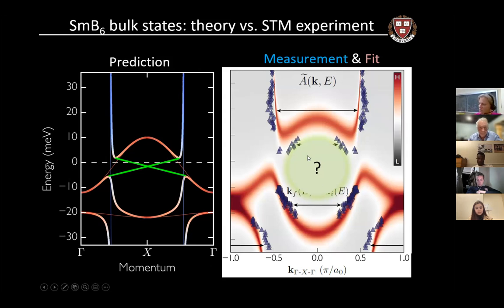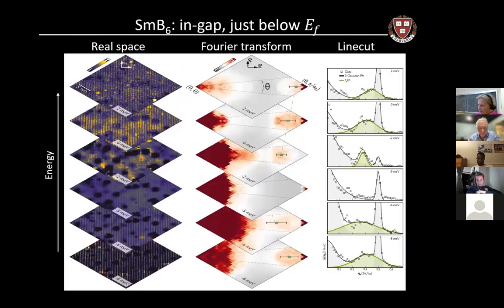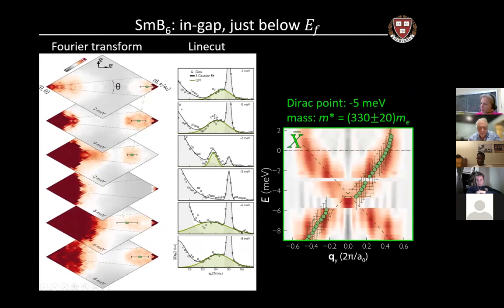And our question was really, do we see the surface states here where the parabolic band crosses the F bands? And the answer is yes, we do. And let me just fast forward here. So as a function of energy, we are seeing this wavelength disperse inwards and disperse outwards again, which gives us the shape of the Dirac surface state that would be the signature of a topological material. So that's the punchline in a 30-second nutshell.